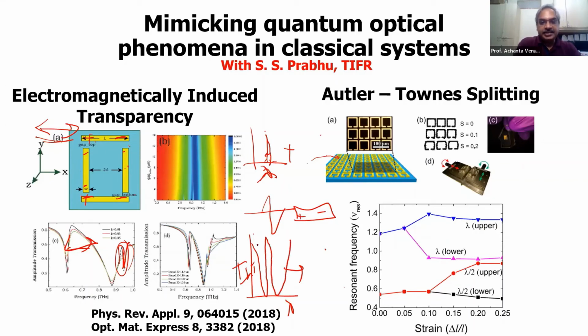Okay. So as the coupling strength increases, right, as the G increases from weak coupling to, say, strong coupling, then what you see is splitting of the energy levels. I showed anti-crossing as one example. The other one, which is known in quantum optics in atomic systems, is the so-called Autler-Townes splitting. So here each energy level is split into two orthogonally polarized resonances. So there is a lambda upper and lambda lower. They have orthogonal polarizations. So that's what is seen experimentally here.